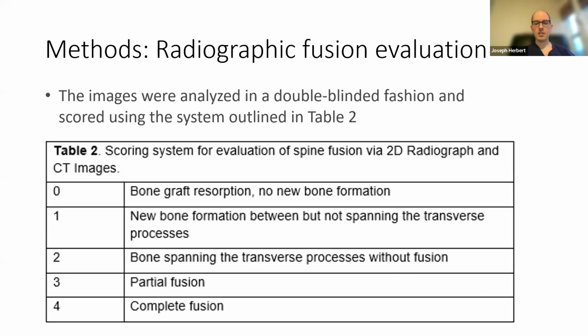So in order to standardize what we're going to call radiographic fusion in these rabbits, we didn't actually come up with a scoring system. We adopted a scoring system from another group, where these would be double-blinded. We'd have two radiologists looking at these, and they would grade it on this scale based on what they thought the radiographic fusion was. 0 being no bone formation, and 4 being a complete fusion.